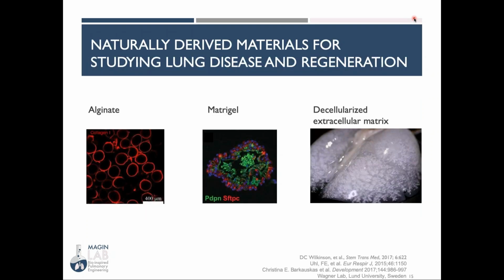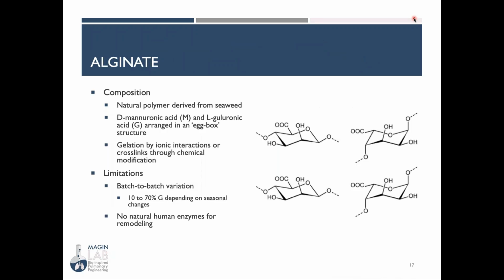So I'll just give an introduction to 2 or 3 materials for each category and tell you a little bit about how they've been used to model lung. So for our naturally derived materials, we'll talk a little bit about alginate, matrigel, and decellularized extracellular matrix. So alginate is a naturally derived polymer that comes from seaweed. It gels by cross-linking through ionic interactions, or it can be chemically modified to be cross-linked in other ways. Some of the limitations to this are a little bit of batch-to-batch variation.